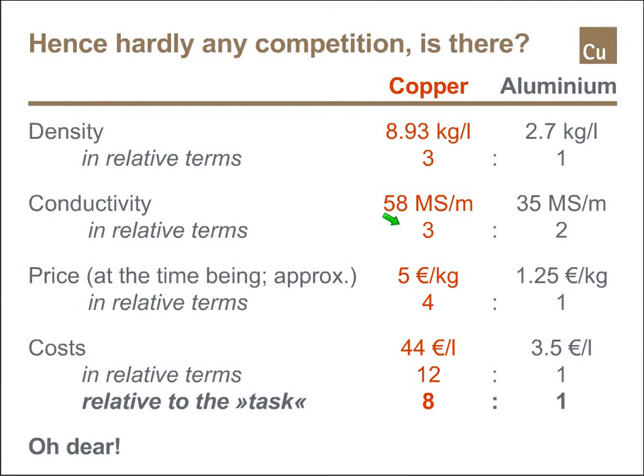Now, is there really hardly any competition between copper and aluminium? To some degree, of course, there is, but as I say, the other differences are quite great. When you look at the density, the ratio is 3:1, copper against aluminium. The conductivity, as mentioned, is 3:2. Now, the price, well, the prices are very volatile, but right at the time, they are roughly 4:1 of copper